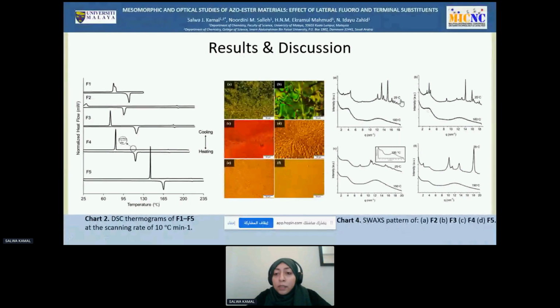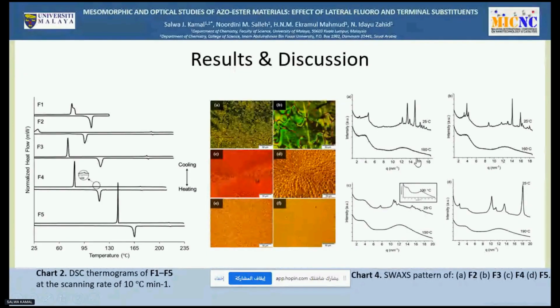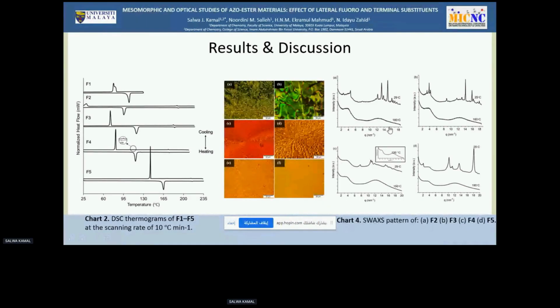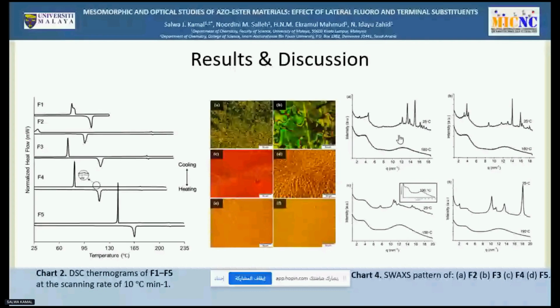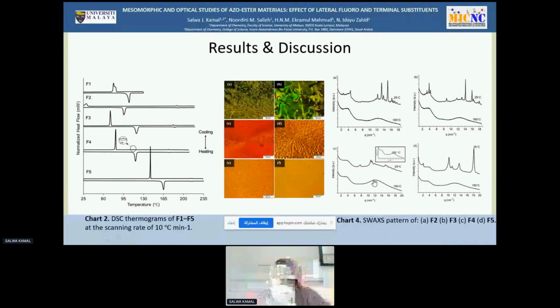As you can see, at 25 degrees centigrade, all compounds showed multiple peaks at wide angle, typical for the crystalline phase, while a highly diffuse scattering peak was shown for all compounds, confirming the formation of the nematic phase.